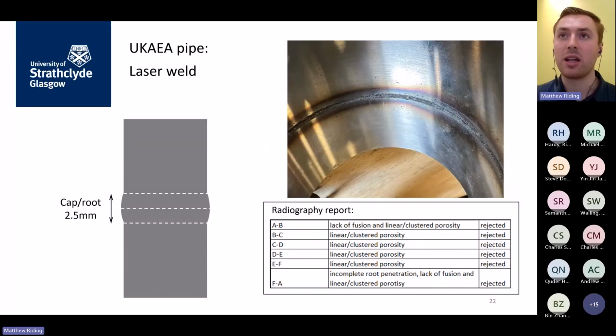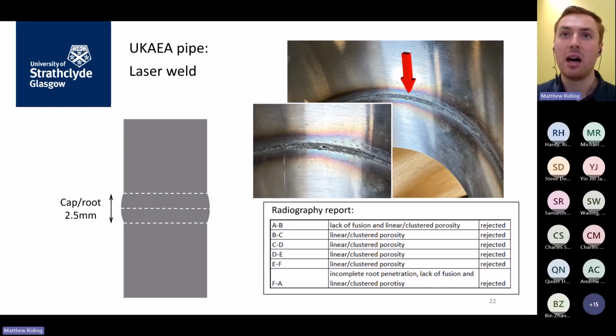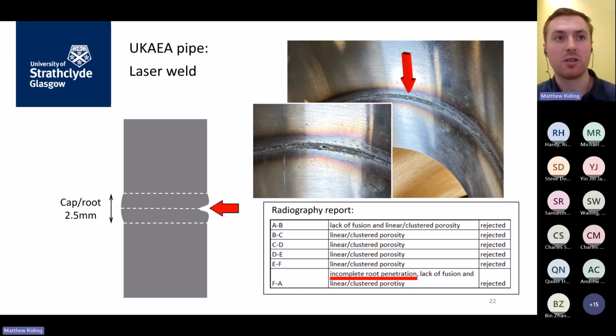And the defect we went looking for was this keyhole defect that's visible from the inner surface, and came up as incomplete root penetration on this radiography report. So that would form something like this in the cross section of the weld, a sort of inward pore on the inner surface of the weld.